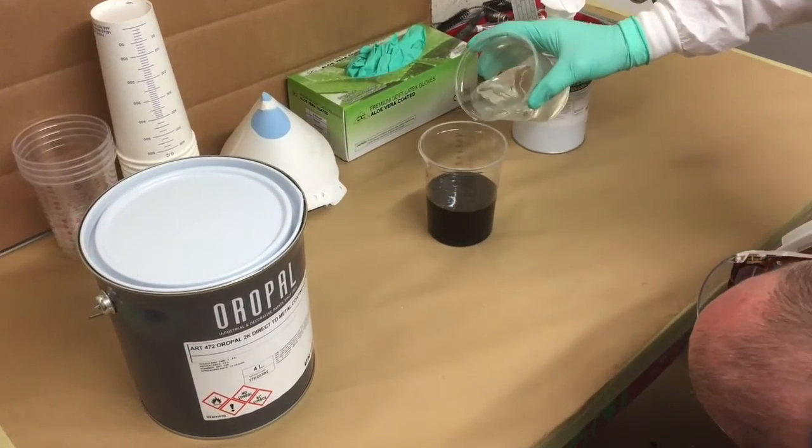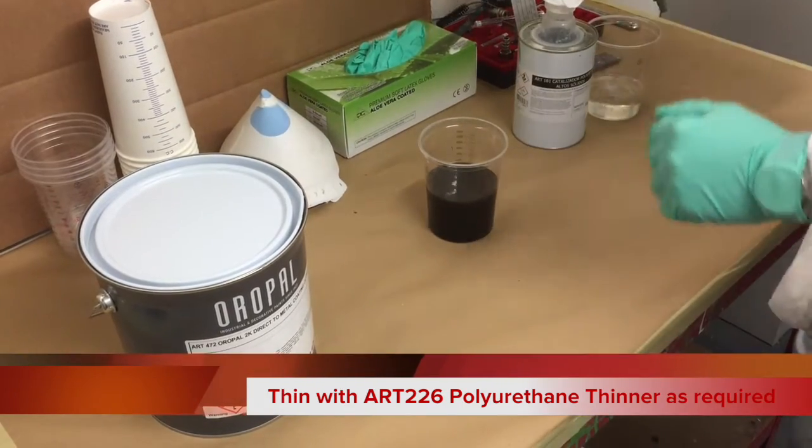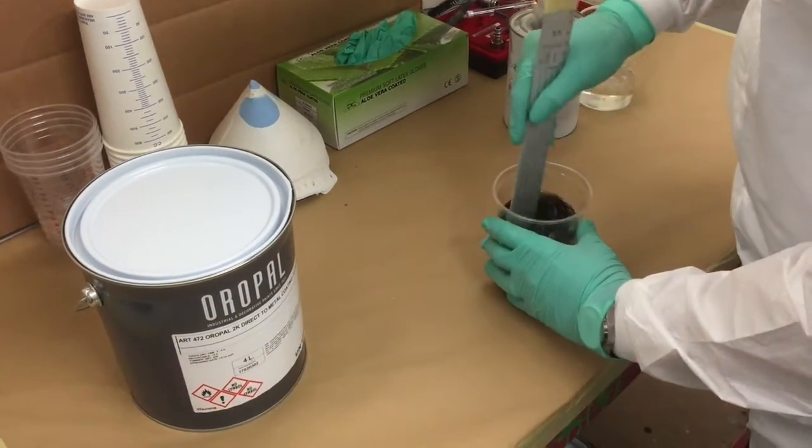Mixed at a ratio of 4 to 1 with Oropal 181 Hardener, it may be thinned dependent upon the application equipment used with Oropal 226 thinners.